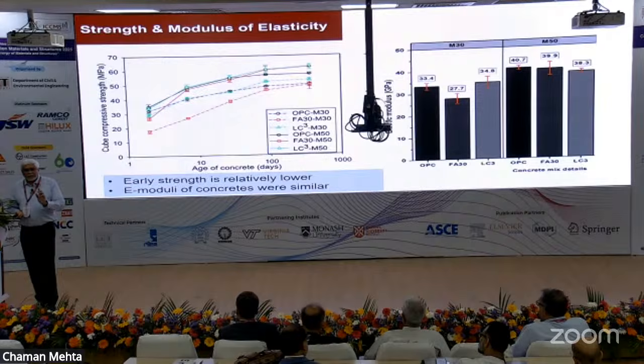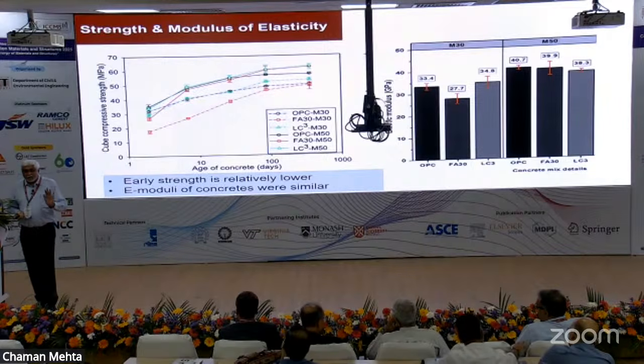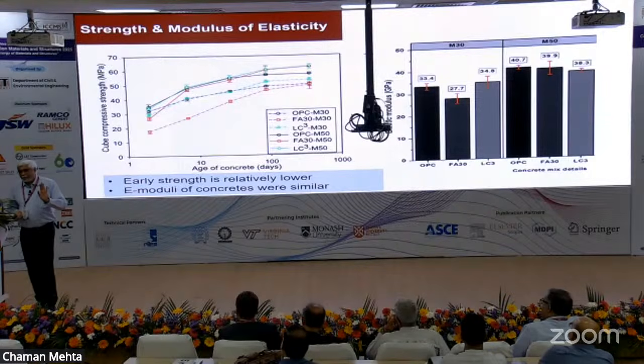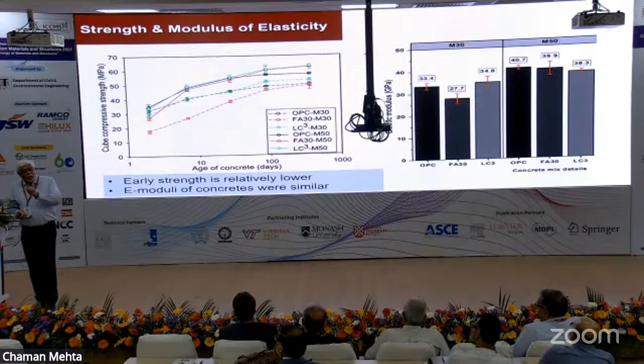Normally now in India, they are asking for 15 megapascal at 15 hours. Okay? It's practically impossible if you have 50% slag, 70% slag, 30% fly ash. So this is now negating the use of special concrete, special binders, blended binders in concrete. So we have to work on that. We have to see how to push up this strength and not worry only about the higher strength concrete.